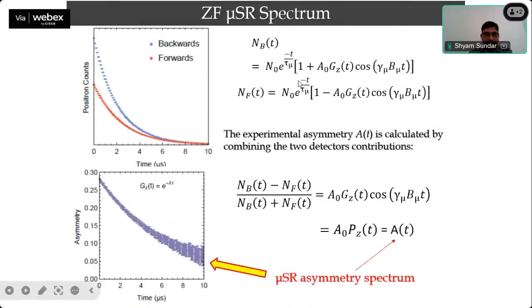But if we take the difference of backward and forward divided by the total number of muon counts, this defines the asymmetry, which is the experimental number which we plot as a function of time. Then we use several different models to explain this, and we get information about the data. In the first top graph, you can see the positron counts as a function of time. Since it's a nuclear decay, this is decreasing as a function of time. When you take the difference divided by the total, you get the asymmetry, which tells about the magnetism in the system.